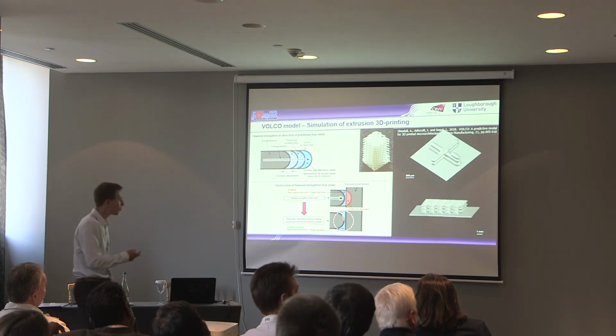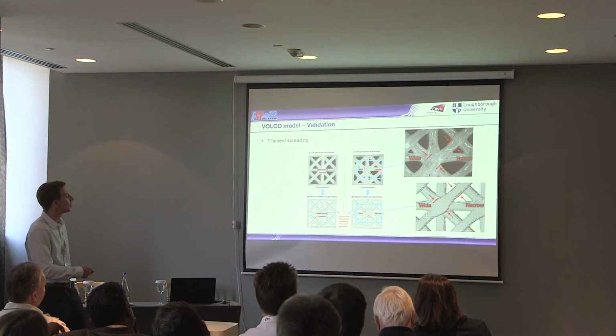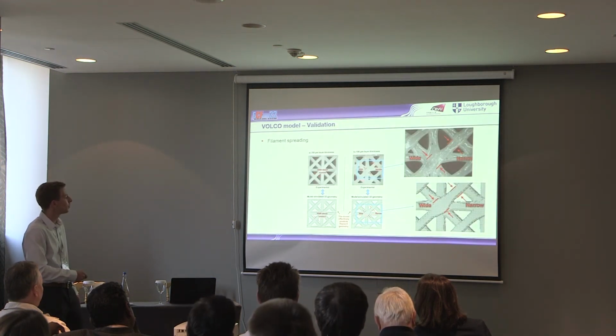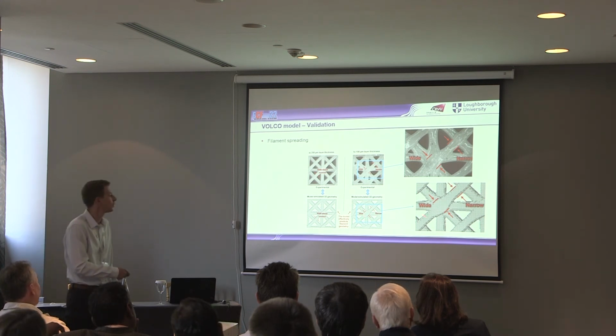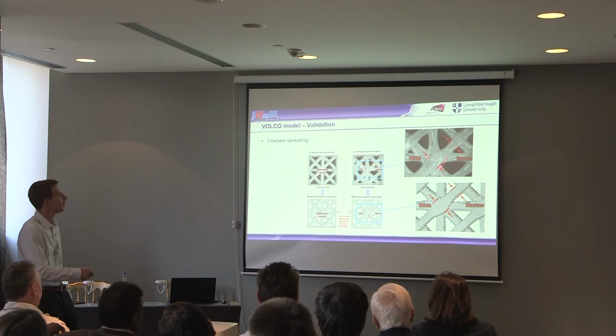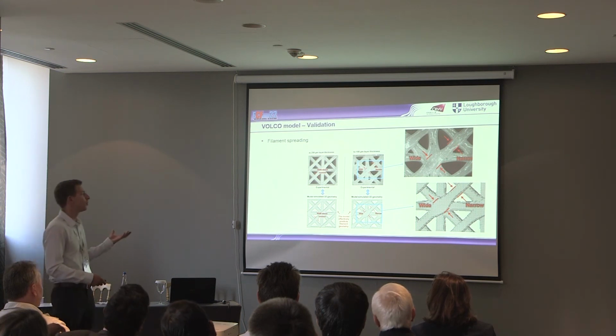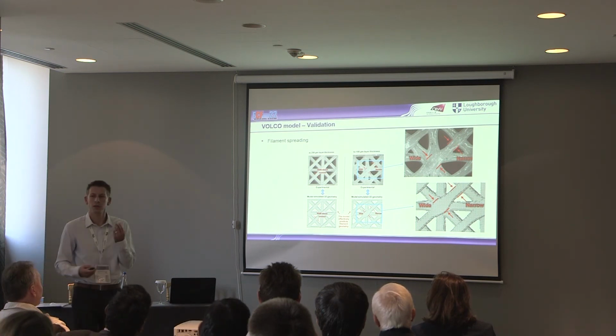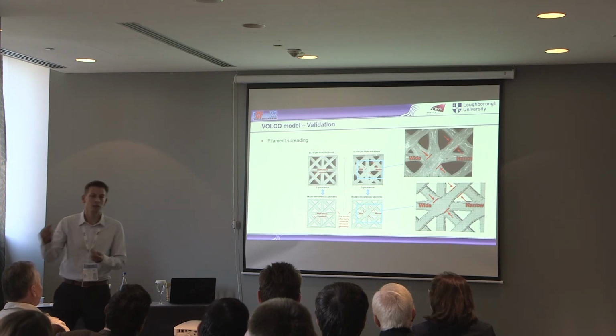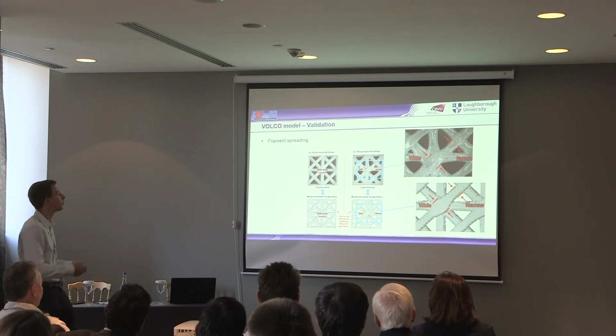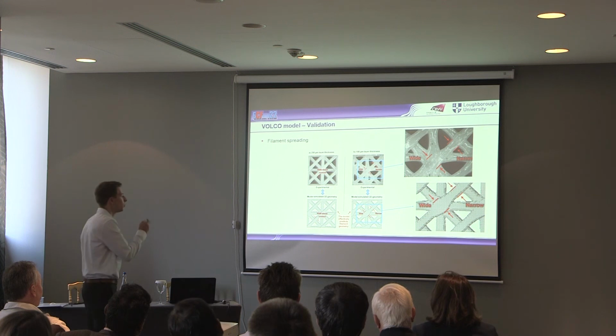And with that, we can then get predictions of how the geometry is at the micro scale. So you can see on this one, the filament is getting slightly wider as it's crossing over the previous filaments, and you can see that this is the model results, that's the experimental results. And that's very important for cell seeding when we're talking about the cells actually attaching to 3 filaments and the contact angle between those filaments and so on, but also for mechanical properties.